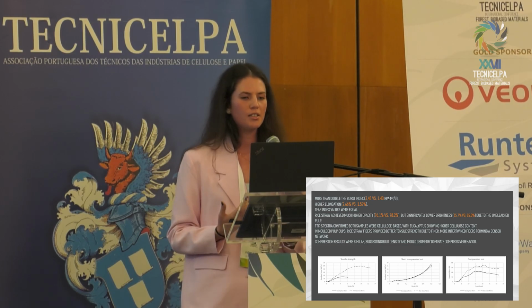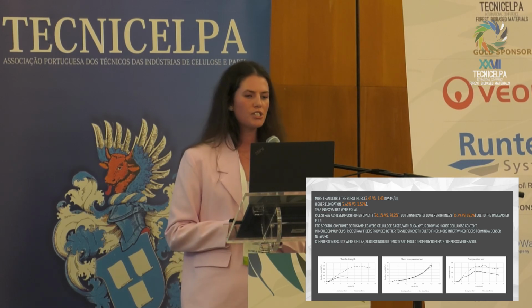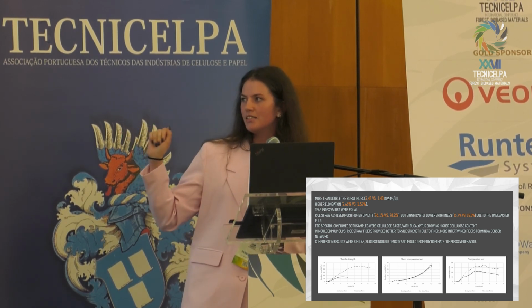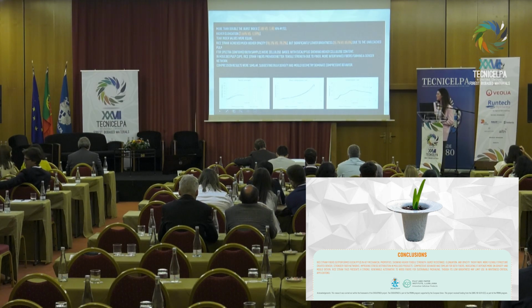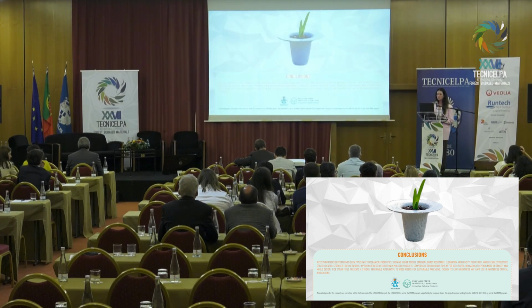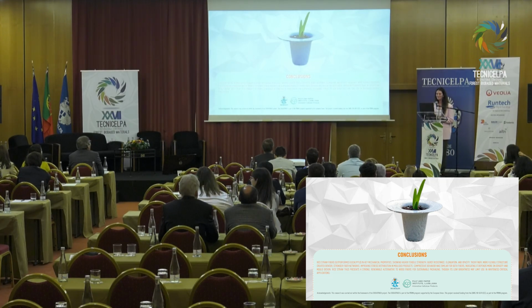In molded pulp cups, rice straw fibers provided better tensile strength due to the finer, more intertwined fiber forming, and compression results were similar, suggesting bulk density and mold geometry dominate compressive behavior. The dotted line is the rice straw fiber, and the straight line is eucalyptus fibers. So to conclude, rice straw thus presents a strong renewable alternative to wood fibers for sustainable packaging, though its low brightness may limit use in whiteness critical applications. That's all from my side.